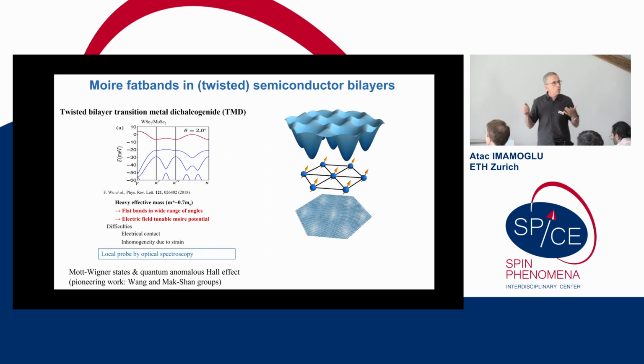Again, this whole thing started, of course, with twisted bilayer graphene by Pablo Jarillo-Herrero and co-workers. What has been particularly interesting, at least from my perspective, in the last few years is that these ideas have been transferred onto semiconducting moire materials consisting of transition metal dichalcogenides, where there are certain advantages and naturally disadvantages. Once you consider two massive Dirac materials like transition metal dichalcogenides, there is no magic angle. So in fact, the angle is a tuning parameter for what these moire bands could be. One could say that's more difficult to do in practice because you get what you get when you make